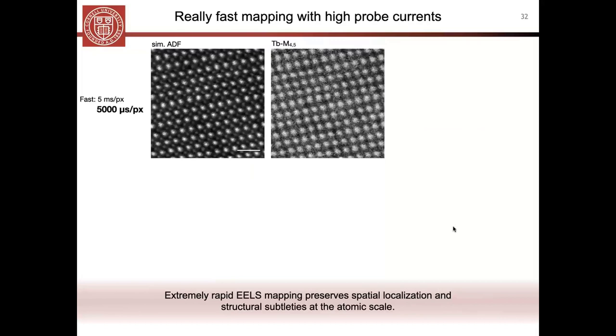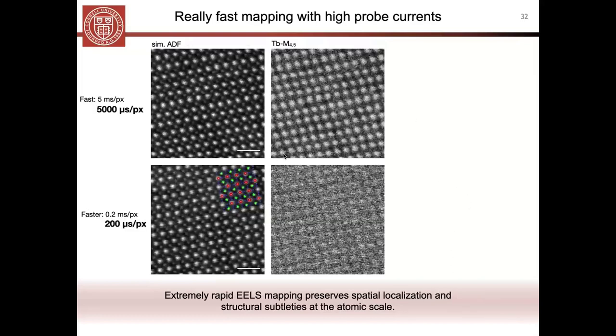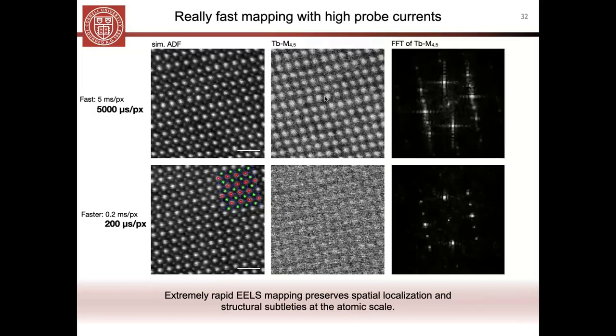And so to convince you that really fast 5,000 pixels per second speed is really necessary, here we can look back to the 5 milliseconds per pixel. Of course, that looks like a very nice high signal to noise map. And you compare to the very fast map. And so again, looking at the terbium, you might say that you prefer this one. But if you look at the FFTs, I will tell you that for the kind of materials physics that we're after, I prefer this bottom one down here because of how well we've preserved this superlattice structure, which you can see again in the reciprocal space information.